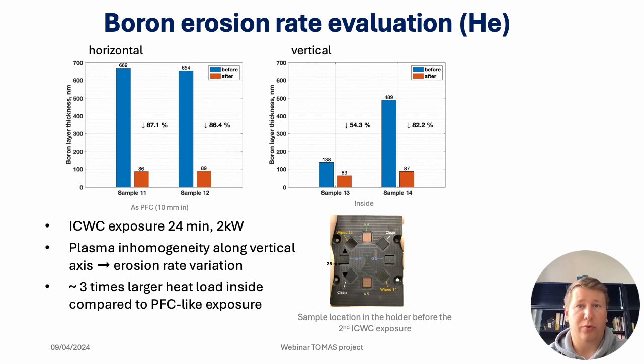Here we see an example of boron layer erosion in helium ion cyclotron wall conditioning plasma at a frequency of 25 MHz and an input power of 2 kilowatts. There were two exposures, each lasting 24 minutes. In the first exposure, we placed the samples horizontally at the plasma edge, and in the second exposure, vertically in the plasma center. So we exposed two graphite boron samples in each exposure. We measured the boron layer thicknesses before and after the exposure, and the results are shown in the figures. Knowing the layer thickness difference and exposure duration allows for calculating erosion rates.